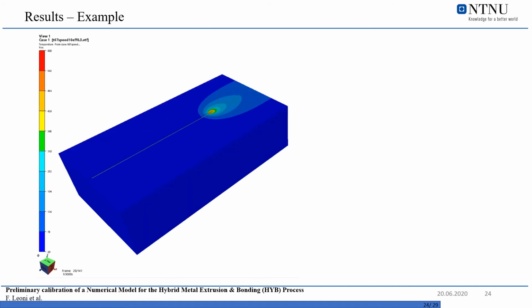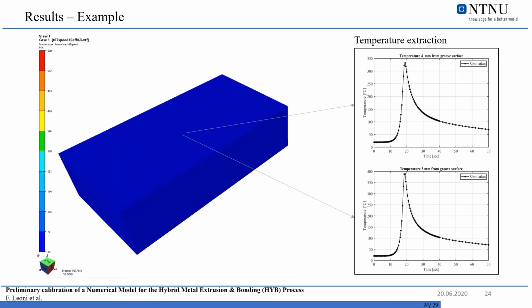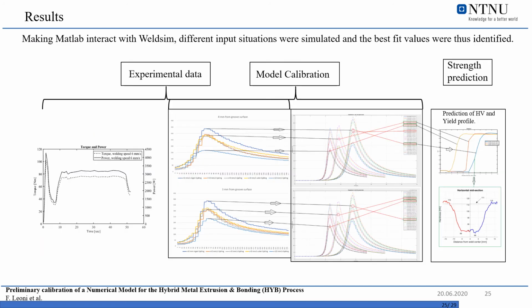So here you can see an example of the plates during welding in the simulation. The temperature field evolves like this, and once the simulation is done, it is possible to extract the thermal field from the points that we set in the pre-processing part. So by means of an interaction between WeldSim and MATLAB, it was possible to run several simulations and find out which was the actual power input to use in order to obtain the same thermal field as in the experiments, and so to obtain the best possible prediction in the microstructure evolution.